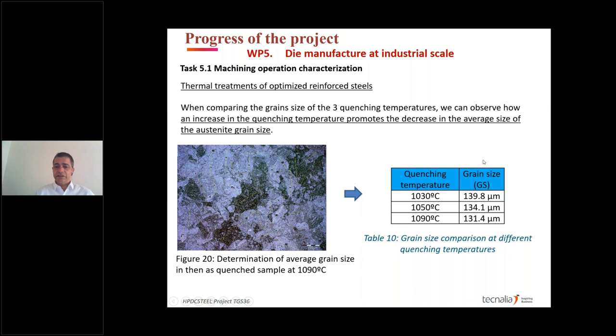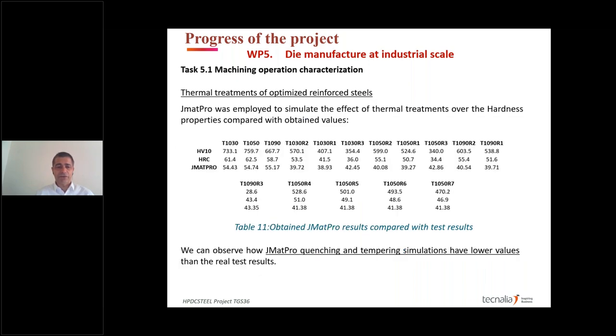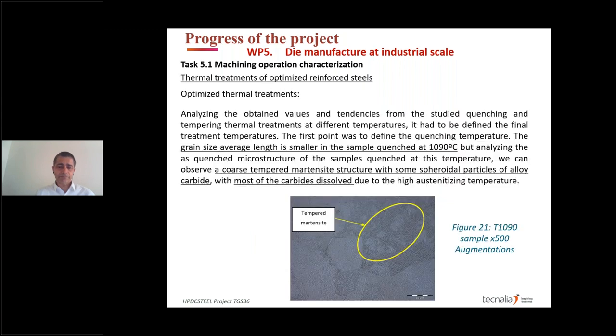So we measure the grain size of the three quenching temperatures, and we obtain that the higher the temperature, the smaller the grain size. That was against the properties, the hardness that we had obtained before. We also tested the JMatPro simulation of the tempering and quenching processes. We see that the values were lower than the real test. It can also be related to them not taking into account the reinforcing matrix.